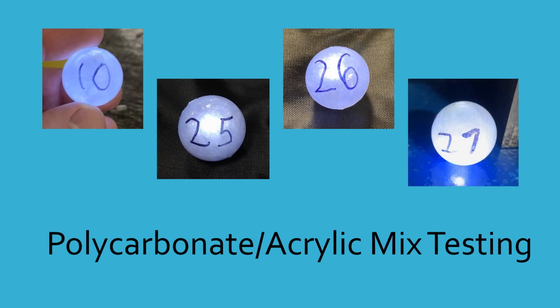The team also tried multiple mixed materials, including a 25% polycarbonate and 75% acrylic mixture, a 50-50 mixture, and a 75% polycarbonate, 25% acrylic mixture. The ideal mixture was found to be the 50-50 mixture with an optimal material temperature of 500 degrees Fahrenheit and an optimal mold temperature of 215 degrees Fahrenheit.